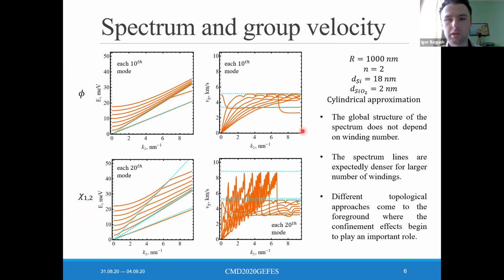Comparing many different results with different approximations and winding numbers, we found that the global structure of the spectrum doesn't depend on winding number. The spectrum lines are expectedly denser for a larger number of windings, and very interesting is that different topological approaches come to the foreground only where the confinement effects begin to play an important role.